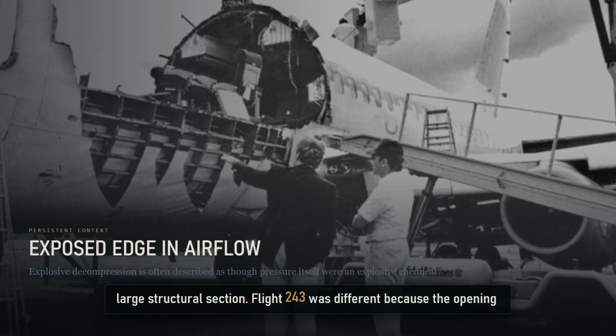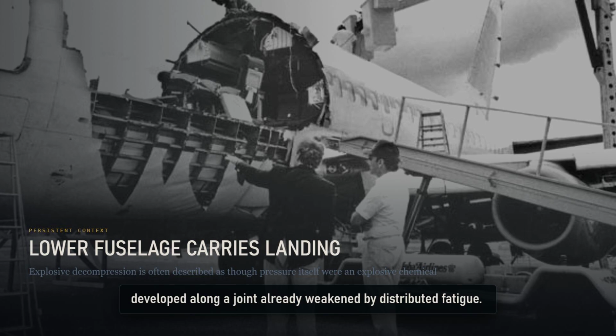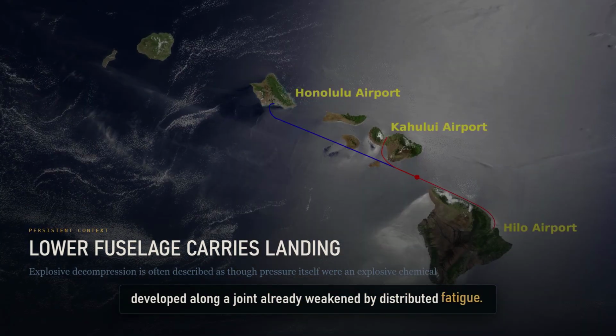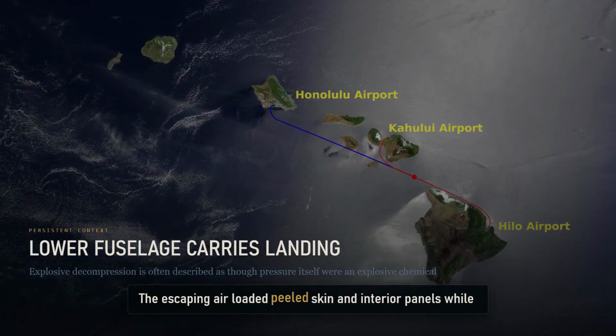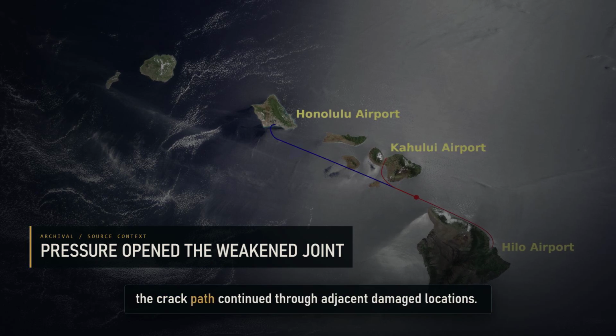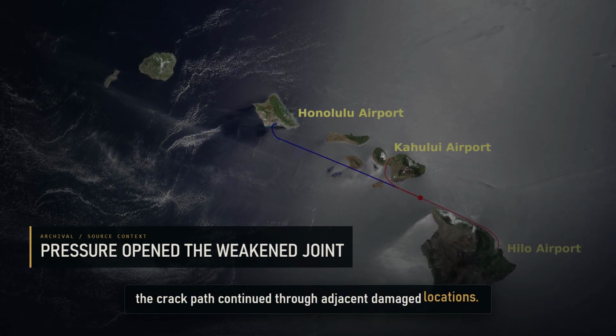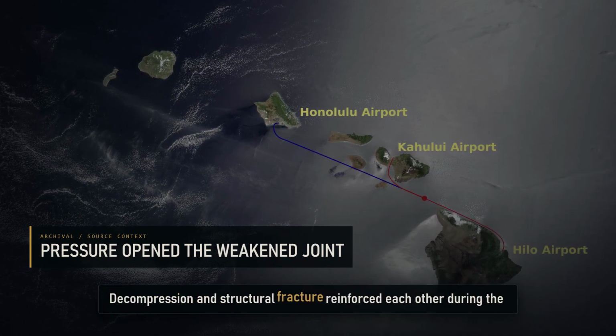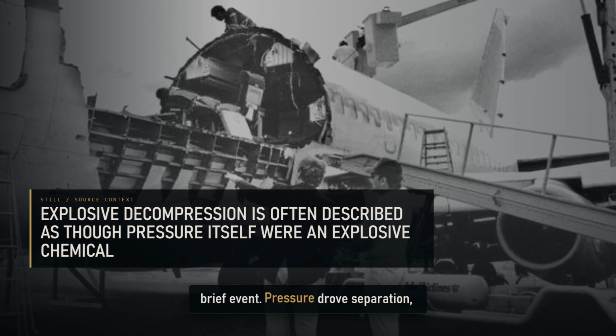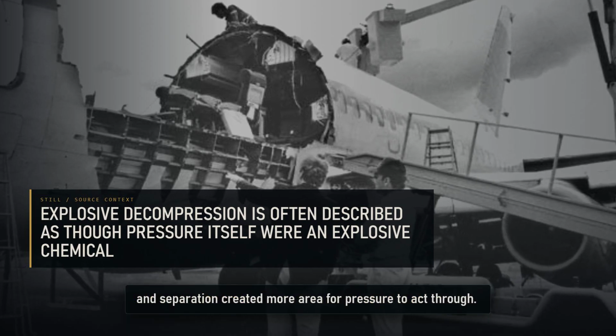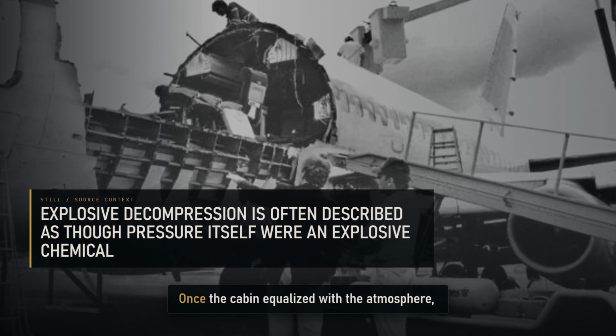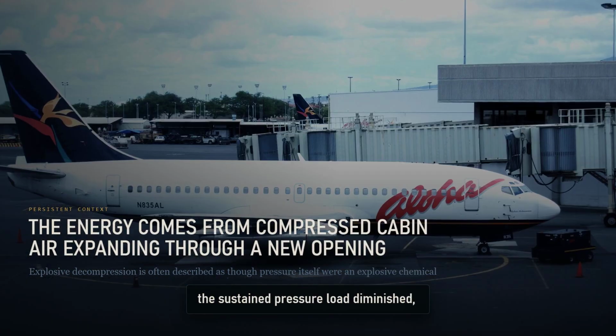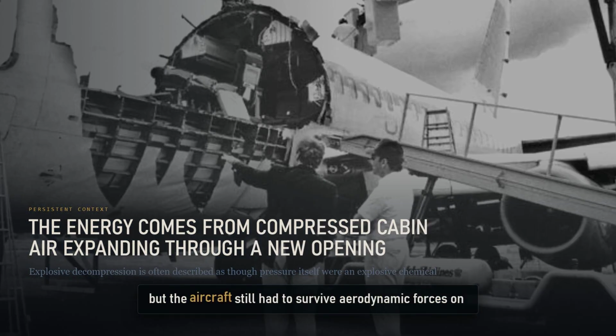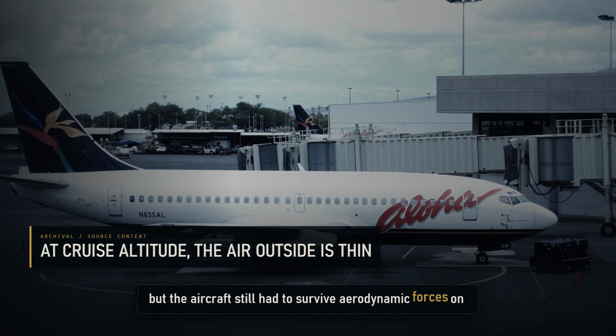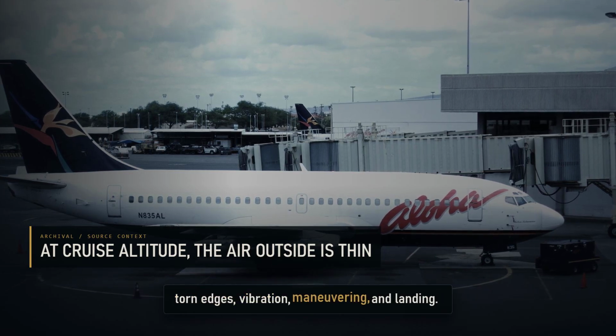Flight 243 was different because the opening developed along a joint already weakened by distributed fatigue. The escaping air loaded peeled skin and interior panels while the crack path continued through adjacent damaged locations. Decompression and structural fracture reinforced each other during the brief event. Pressure drove separation, and separation created more area for pressure to act through. Once the cabin equalized with the atmosphere, the sustained pressure load diminished, but the aircraft still had to survive aerodynamic forces on torn edges, vibration, maneuvering, and landing.